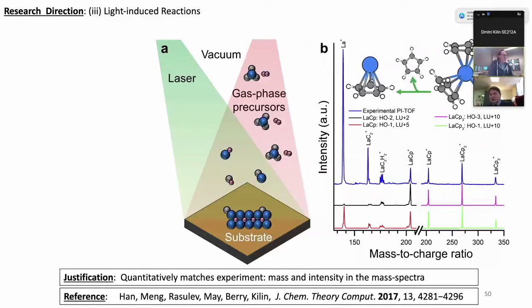So nano semiconductors are fine, nano metals are fine, but nano insulators were a challenge, because if we have a nano thick or nano thin layer of insulator, it starts leaking charge. With standard silicon dioxide, the material from sand, this is a problem. But if instead of oxide of silicon we use oxides of heavy elements like lanthanum or several others, it will be an ideal insulator on a monatomic layer, so really thinner than a nanometer.